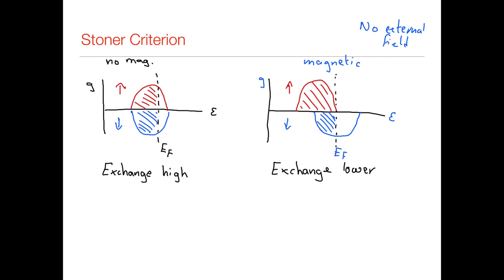Now that can't be the only factor, because if that was the only case, all of these transition metals would become magnetic, and we know from the first row only iron, nickel, and cobalt are magnetic. What's in tension against this is actually the kinetic energy of the electrons.